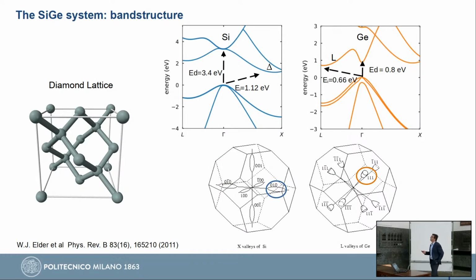So these two materials share the same crystal structure as diamond, so this tetrahedral coordination repeated periodically in space. These are the two band structures, where again we have energy and the crystal momentum. So we see that they have quite similar valence bands, and the conduction band for the two materials has some differences. They are both what we call indirect semiconductors, so the minimum energy distance between the valence band and the conduction band is not in the same place in crystal momentum space.